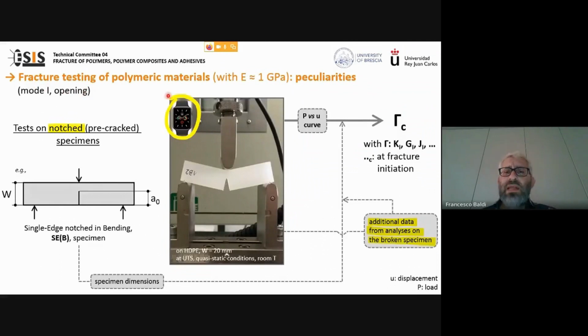Now I would like to focus the attention on some peculiarities related to fracture testing of polymeric materials. If I consider mode 1 opening mode, tests on notched specimens, I consider, of course, specimens with a notch inside. This image shows a single-edge notched in bending specimen. Therefore, I prepare the specimen, I notch the specimen, I execute the test in quasi-static conditions. Of course, I have to take into account always the time. They are viscoelastic, and I cannot forget this fact.